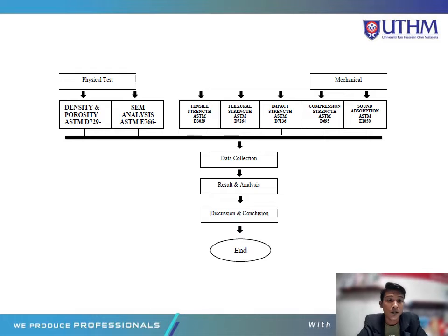After the molding process is complete, there will be curing time. After all 7 samples with different ratios of PEFB are left for about 24 hours of curing time, there will be 2 types of tests, which are the physical test and the mechanical test. For the physical test, I will do density, porosity, and SEM analysis, while for the mechanical test, there will be 5 types of tests: tensile strength test, flexural strength test, impact strength test, compression strength test, and sound absorption test.